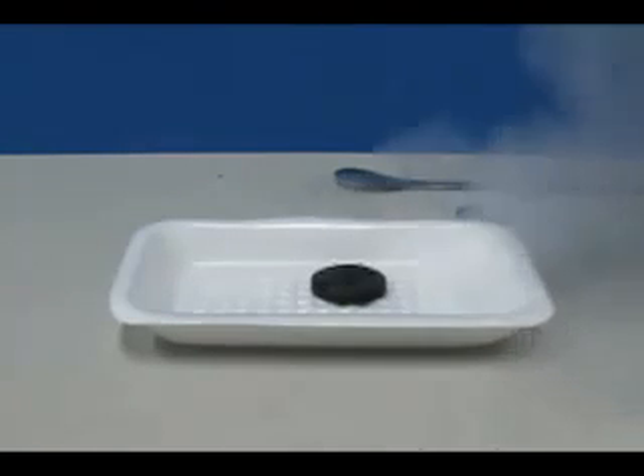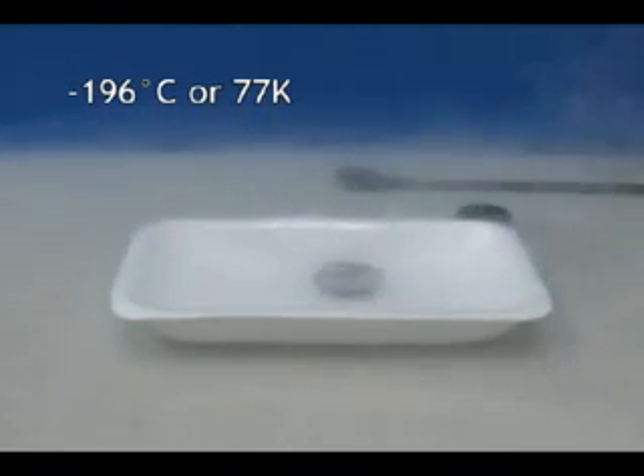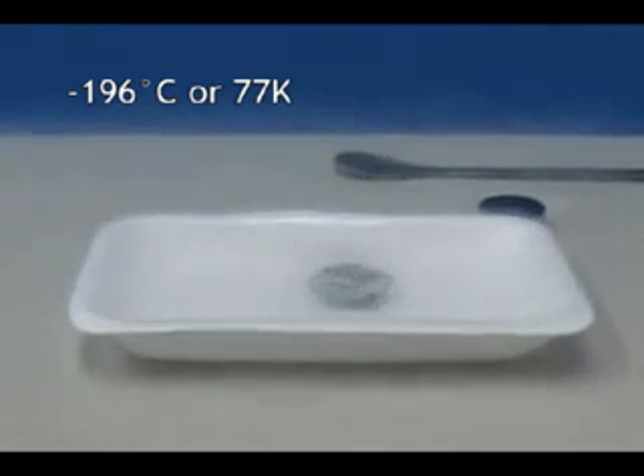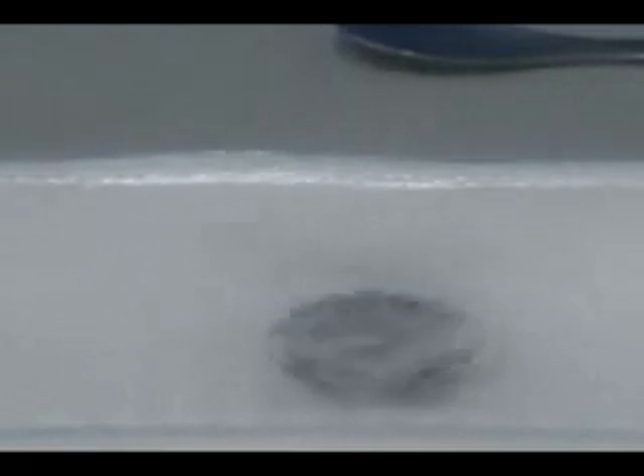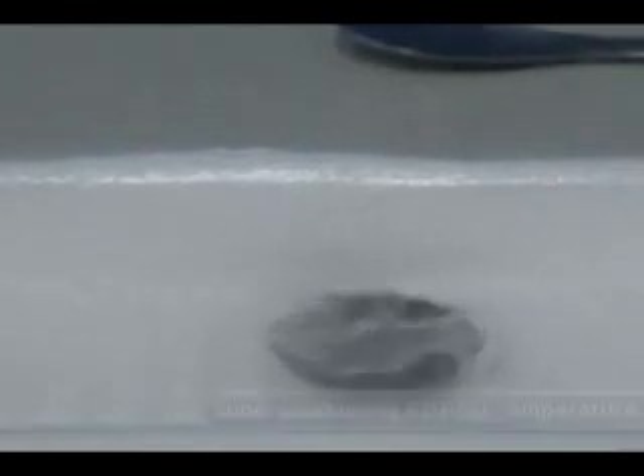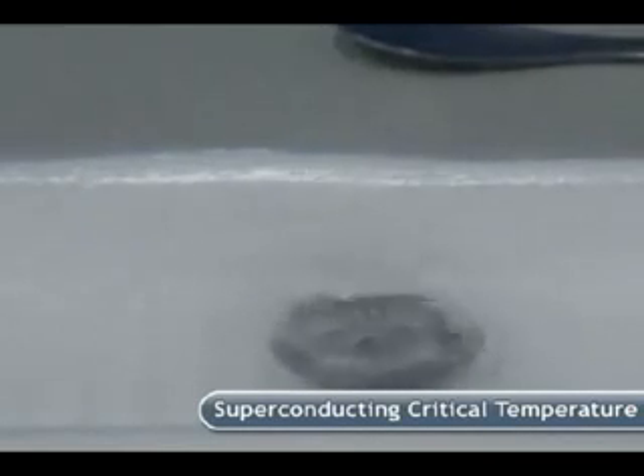The smoking liquid that is being poured out on the superconductor is liquid nitrogen. Its temperature is 196 degrees below zero Celsius, or 77 degrees Kelvin. The liquid near the superconductor undergoes intense boiling due to the heat that the liquid nitrogen absorbs from the superconductor. The liquid nitrogen becomes nitrogen gas, and the temperature of the superconductor drops gradually. When the boiling ceases, it indicates that the superconductor and the liquid nitrogen are in thermal equilibrium. This indicates that the temperature has cooled below the superconducting critical temperature, or 91 degrees Kelvin for the yttrium barium copper oxide compound, and has established superconducting properties.